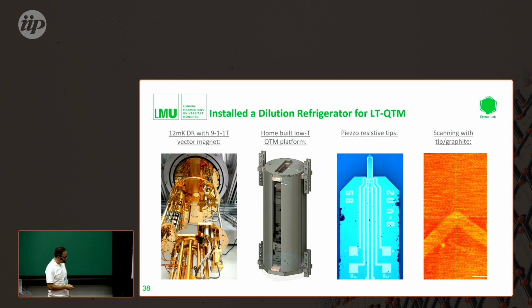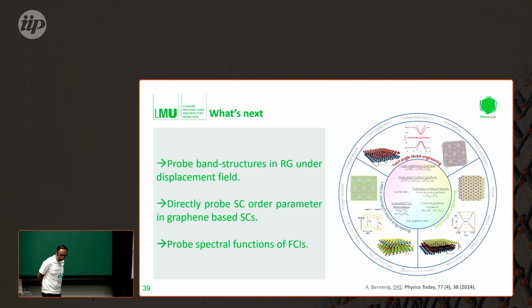To give a bit of an outlook, what I would be excited to see or to do as a community, because now there are several groups trying to build these QTMs, is, for example, to probe the band structure of rhombohedral graphene under displacement field. In this exciting time for rhombohedral graphene, you are always limited by the device architectures. You have top and bottom gates, so you cannot easily do STM or ARPES on it. So in order to get some spectral information, maybe this is a technique that could give some information about it.